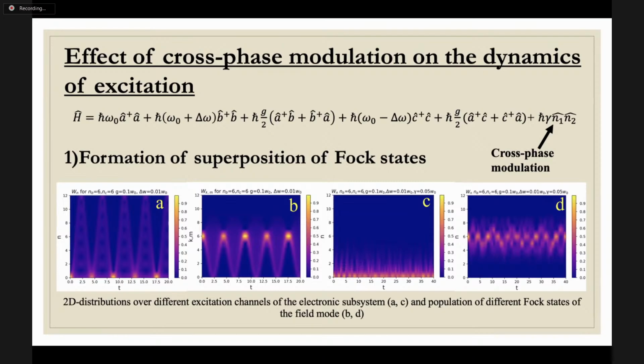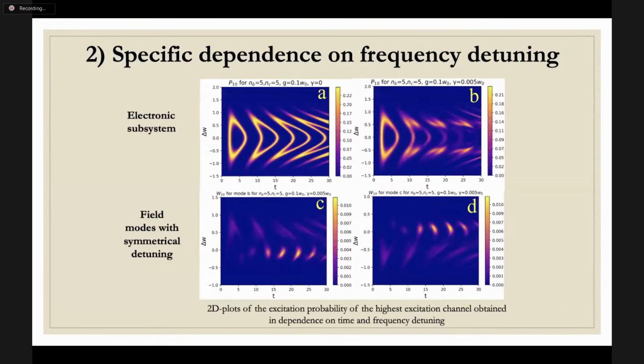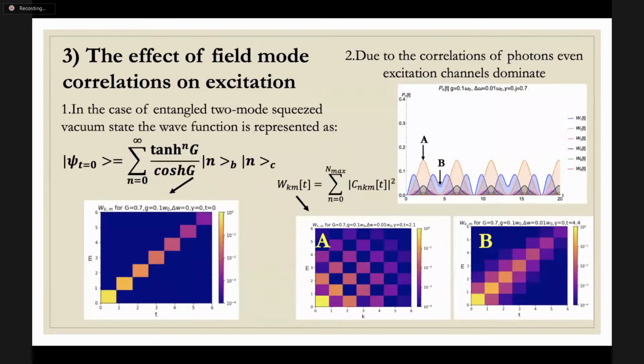And this effect is possible due to the energy exchange between the field modes via the coupling with the electron subsystem. A rather specific distribution of excitation was found in dependence on the field frequency detunings, and due to the effect of the cross-phase modulation, two optimal frequency regions symmetrically detuned from resonance are found to provide maximal excitation in the nanosystem. In contrast, the similar distributions obtained for the field modes population appear to be nearly symmetrical and reveal much lower optimal detunings.